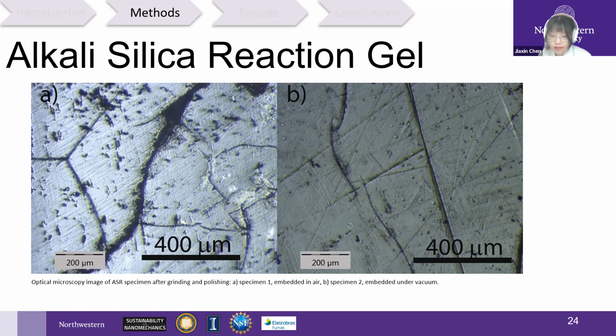The other, which we call specimen 2, we embedded under vacuum. In other words, during vacuum embedding, the epoxy resin is pushed into microscopic pores, resulting in a smoother surface. Definitely, we can see it here on the right-hand side. From both images, it seems our surfaces look smooth, even though there are some cracks. But because of the pre-cracks seen in the microscopic images, we know that when we design the parameters of our scratch testing and indentation, we need to have a shorter length and force limitation.